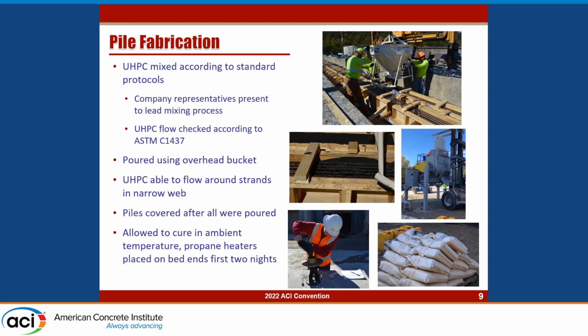Once all the piles were poured, we covered them to retain as much heat and moisture as we could, and they were allowed to cure largely in ambient temperature. Now, during the first 2 days when our strength gain was most critical before detensioning, we had some unexpected chilly nights in Alabama. So we placed propane heaters on each end of the bed to maintain a temperature of about 75 degrees, but we didn't apply any additional heat or anything.